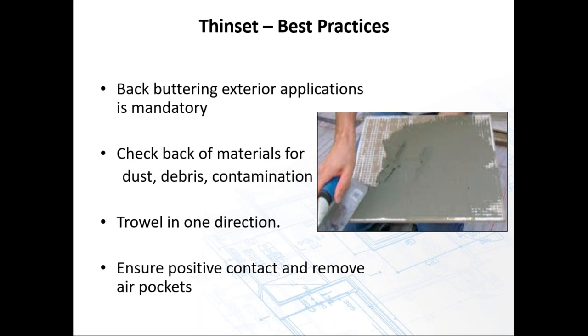Occasionally, as the tile is going up, pull down a piece of tile, look, and make sure that the coverage is there. Check the material for dust or debris or any contamination that would prevent a good bond of the tile coming into contact with the mortar. Remember, any dust blowing in the air, any debris acts as a bond breaker. Just like if, as you're rolling out cookie dough, you put flour on the counter, the dough doesn't stick to the counter. If you're putting up mortar and dust is flying through the air, that dust is now acting as a bond breaker. So it's important to make sure your work area is protected so we don't have dust attacking the mortar until the tile is set into it properly. Ensure that there's positive contact, removing air pockets. The other critical part of this is troweling in one direction, so that the ridges of the trowel marks from the tile, back buttering onto the tile, onto the substrate, are locking it together, becoming like a big zipper.